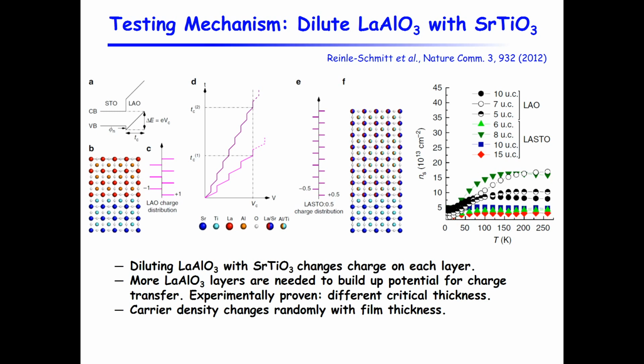to get the 2D electron gas. If you do look at the carrier density for different thickness layers, though, you'll see that it's kind of random. It doesn't really show systematics, and the value, this is 10 to the 13th. Let's say if you have a lanthanum aluminate layer of 10 unit cells, you will get something like 5 or 6 or 7 times 10 to the 13th. So it's random. It's not systematic. And the number also does not really match what people expect.